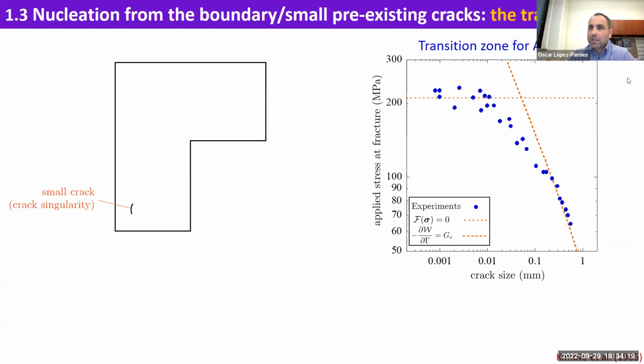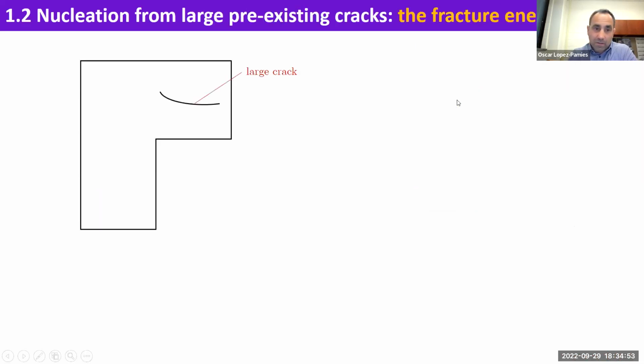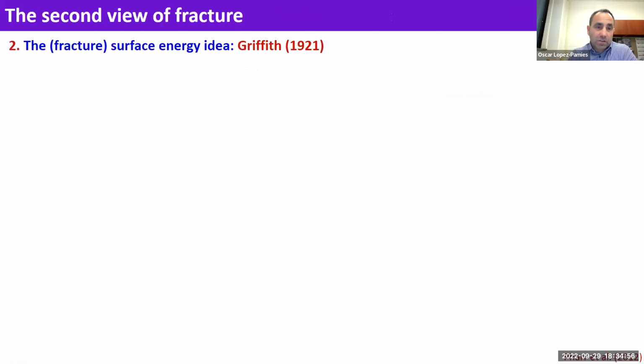So this is a typical experiment on alumina, but you can think of this for any material really. You notice here that as you make the crack size smaller and smaller, there is quite a bit of scatter in the vertical direction. That means that the critical force at which you're going to nucleate cracks is not deterministic, it's stochastic. It is well understood why this is the case. Strength, as opposed to Griffith fracture, is the macroscopic manifestation. I'll show you a picture